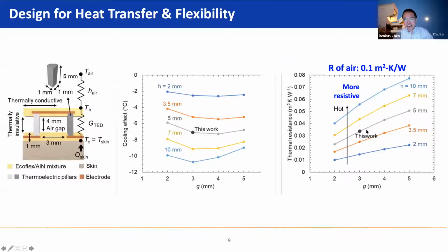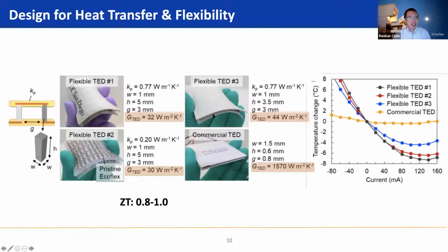And the reason is under this condition, the thermal resistance of the device itself is about 0.03 meter square Kelvin per watt. And that's comparable to the thermal resistance of heat transfer coefficient to the air, which is about 0.1 meter square Kelvin per watt, or heat transfer coefficient of 10 watt per meter square Kelvin. And we can actually show the importance of this design. So for example, if you use a commercially available off-the-shelf thermoelectric device, they typically have very high thermal conductance of the device itself because they are designed for cooling high power laser devices, for example. And so this conductance is usually over 1,000 watt per meter square Kelvin. And our design typically has conductance around 30 to 40 watt per meter square Kelvin. And so you can see with our design, you can have a much larger temperature drop or better cooling compared to the commercial ones.